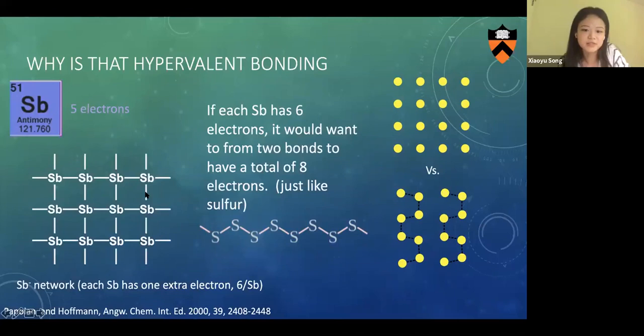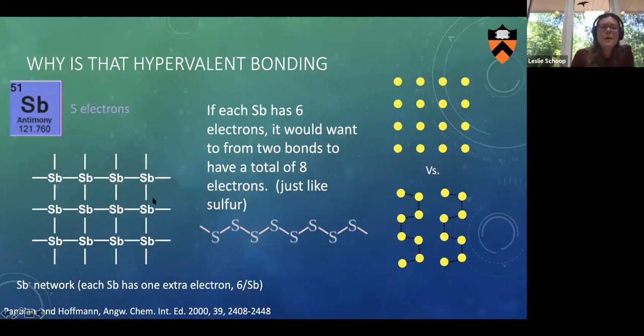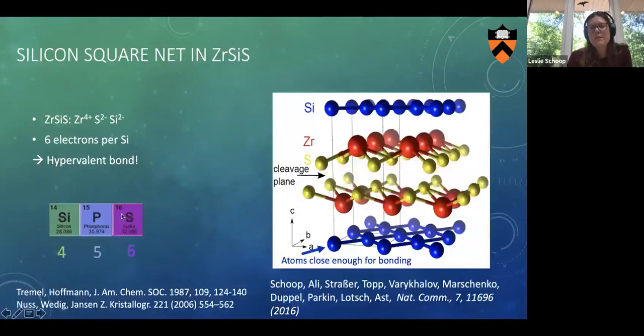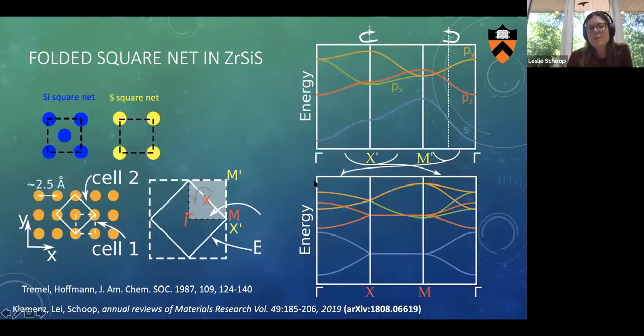So the Fermi energy, this hypervalent bond, what it does is that it stabilizes the electron count of 6 electrons per net atom. So if you look at this band structure, now this is a folded band structure, so you need to count double. That means that because it has 6 electrons per atom, so 12 here, we fill the S band twice. So this is 2 electrons or 4 if it's doubled. We fill the PZ, which is below, with another 2. And then the PX and the PY, they're degenerate. So we fill only half of it.